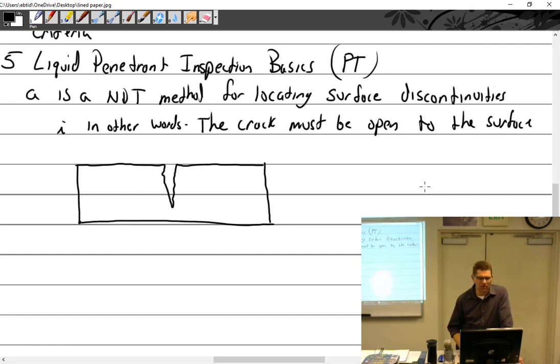All right, and the reason why is, okay, if we use glass, sand, garnet, something like that, this crack is going to peen itself over. It'll bring the metal and stretch the metal over. This is kind of why you're having problems with the cylinder today, because that had been done. So it can bridge that little gap. Then we've sealed that up. Now we're not going to get anywhere with that. So we can't do that.